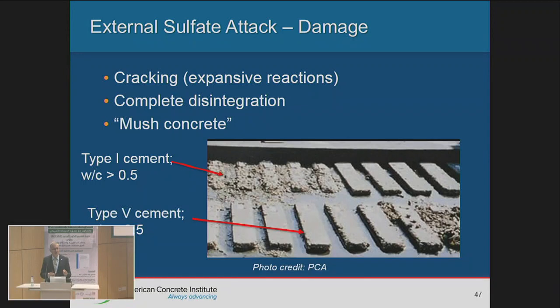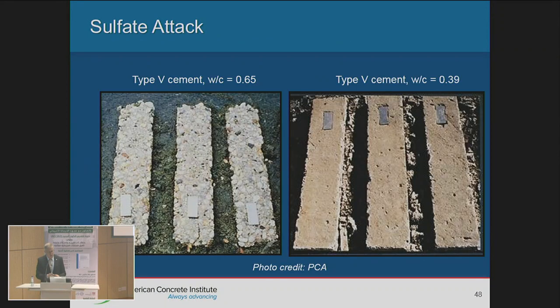Because we know that sulfate really attacks the paste, the concrete paste, right? It attacks it. Whereas here, we have type 5 cement with less than 0.5 water cement ratio. So the water cement ratio plays a role. The type of cement also affects the behavior of concrete. Here, we have two sets of specimens, both of them with type 5 cement, but different water-cement ratio. And you notice that the one with the higher water-cement ratio has more deterioration than the one with the lower water-cement ratio.